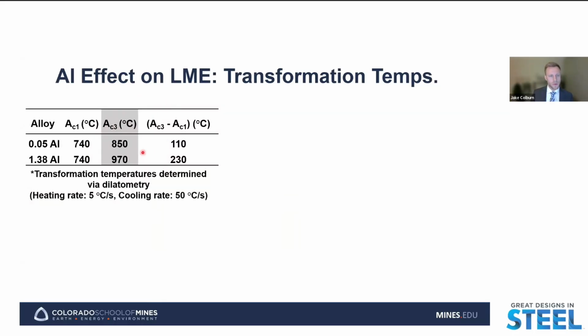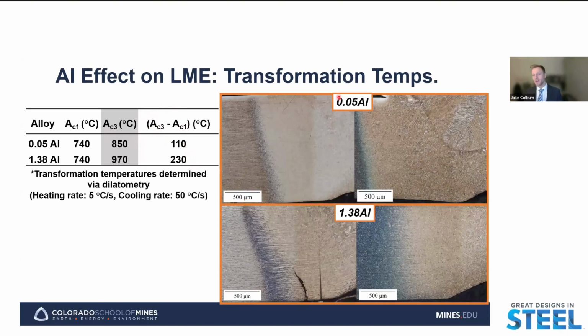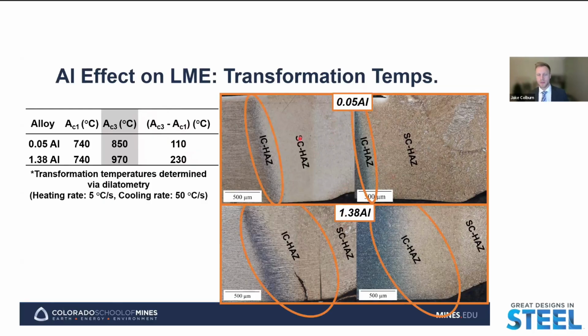which is then also going to increase the width of that intercritical transformation temperature range, that being the difference between those two transformation temperatures. And so if we again go and look back at the high aluminum and low aluminum optical micrographs of these welds, what we see is again indicative of these transformation temperatures, where we see a smaller intercritical heat affected zone width for the low aluminum alloy at both of those currents as compared to this wider intercritical region that we see for the high aluminum alloy, where there's still ferrite present in these regions.